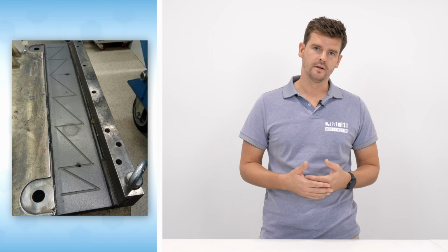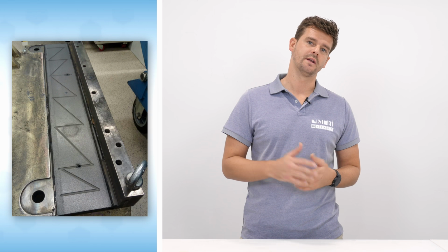With the flowable and wear-resistant WEICON WR, an expensive tooling base was renewed by means of casting. First of all, the original coating was removed by means of heating it up over 200 degrees Celsius. It is important to overfill the space slightly. Then you can be sure that enough material has been poured in. After curing, the surface was remachined by milling and cooling channels were inserted. This procedure has many great advantages. The old damaged tool could be restored within 24 hours, and severe costs and delivery times were avoided.